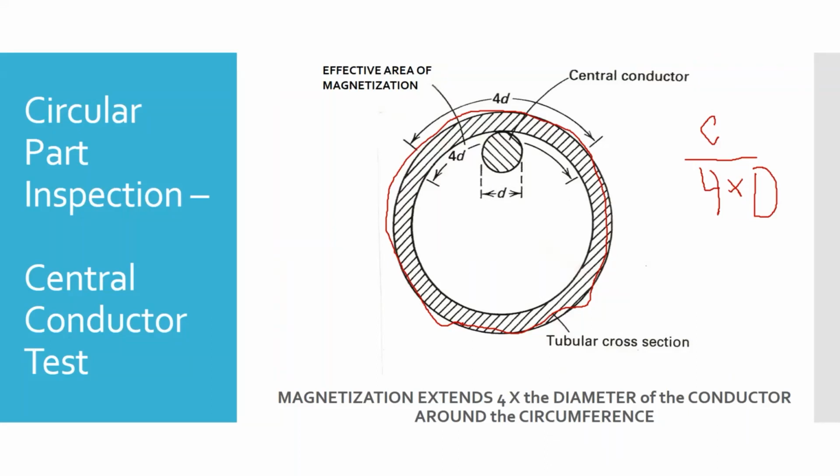If you know a part is about 2 inches across, right? And what's pi? 3.14, right? Roughly. Well, let's just call it 3.2. So if the part's 2 inches across, we multiply that by 3.2, that gives us 6.4, right? Now, what if our rod is a 1/2 inch in diameter?